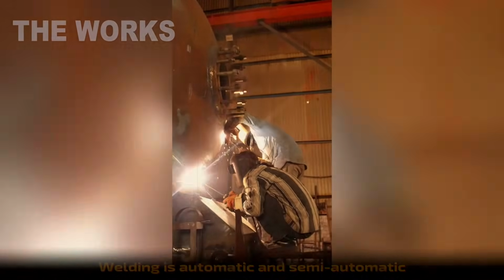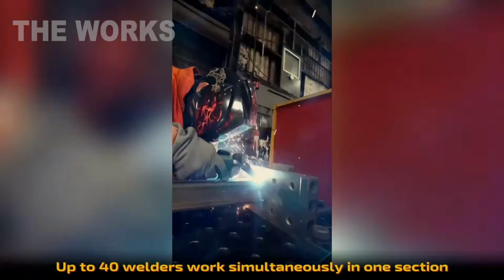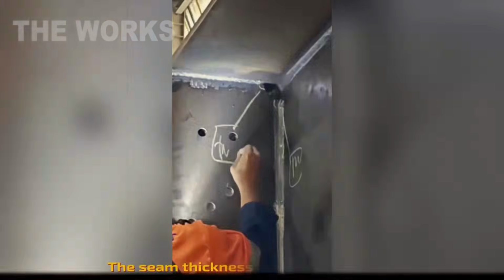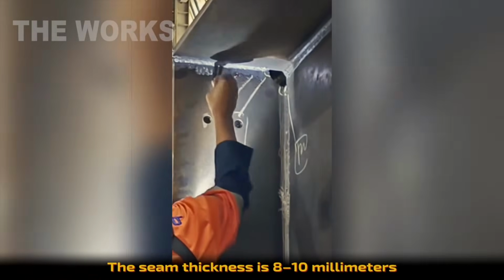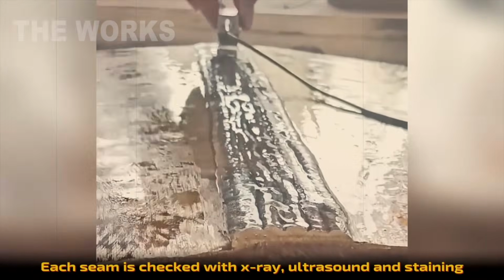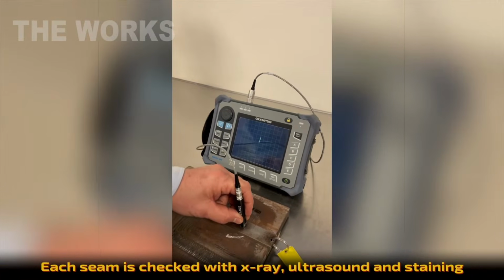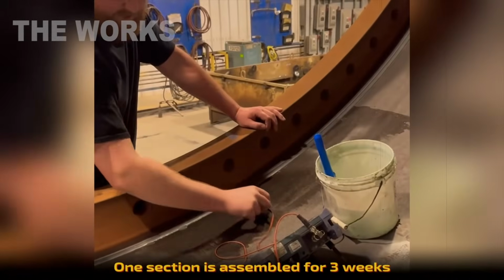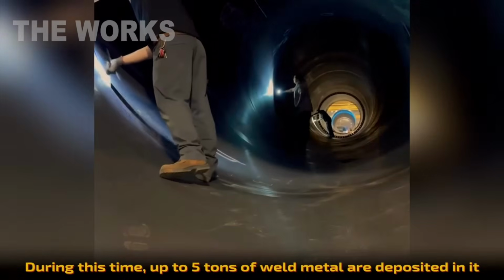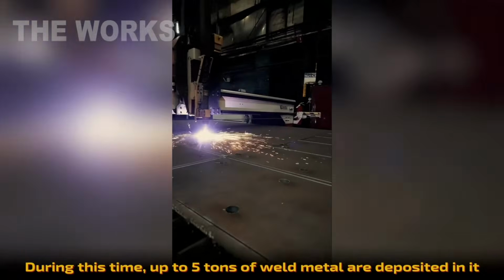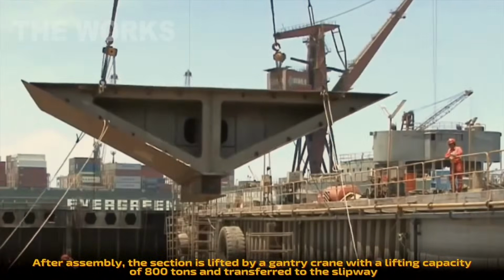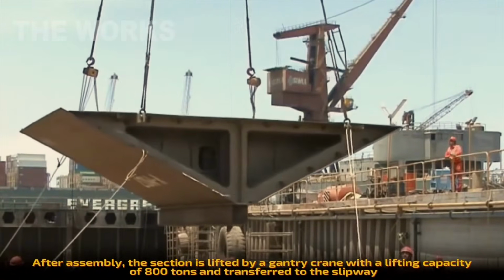Welding is automated and semi-automated. Up to 40 welders work on a single section simultaneously. Weld depth runs 0.3 to 0.4 inches. Every seam gets checked. X-ray, ultrasound, and dye penetrant testing. One section takes 3 weeks to complete. During that time, they lay down 5 tons of weld metal.